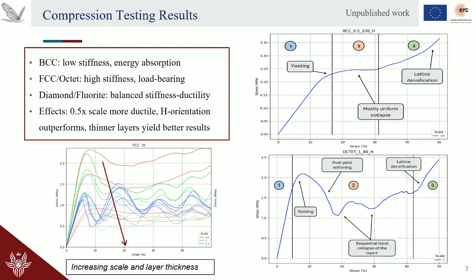Here are the results of the tests performed, and they are very in line with the literature. We see common behaviors. For example, the BCC cell shows low stiffness and high energy absorption, but that's no wonder because it has a very bending-dominated mechanics. And octet cells have a mixed behavior because they also have a lot of straight pillars that act as stretching-dominated regions, so those kinds of cells are high in stiffness and high in load bearing. That's just to show you that the manufacturing was done correctly. So we can move to the next section.